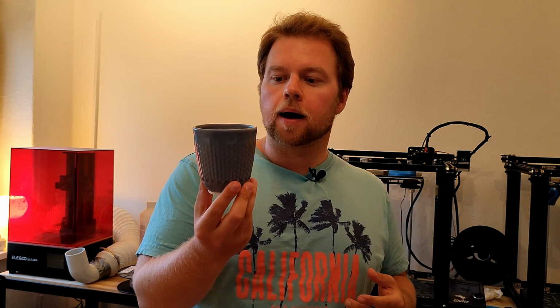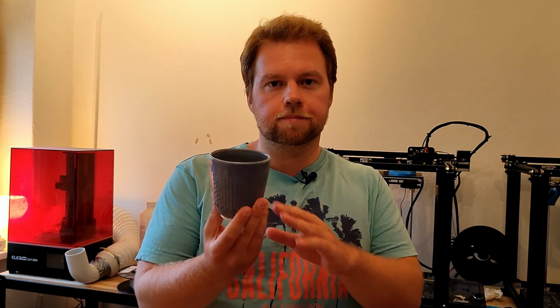And after all of that, what happens is that all the water evaporates from that item. All 3 main components of the mixture still stick together. And then you put it into a kiln and burn it for 13 hours at about 950 degrees. Well, it climbs up to that temperature. One of the components melts, glues it all together, and you get that ceramic item. Afterwards, you can glaze it and then burn it again, doing a glaze firing. And then, for instance, you get something like this here, which is one of the cups that I design and produce. It's that model that you saw in the video, but the glazed version of it.